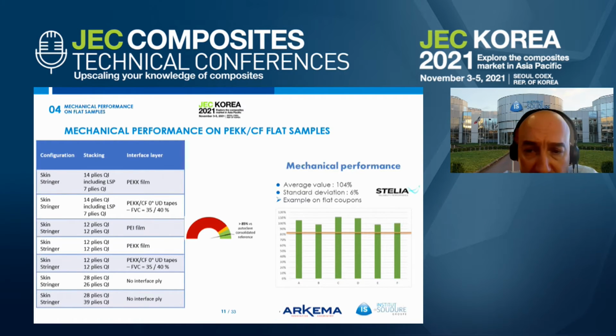If we have a look first on the right side of the slide, this is an example of mechanical performance that we can get on a study that we are running right now with Stelia, but this is illustrating what we get usually. So if we compare the mechanical performance of the welding joint with the reference, in this case, we are about 100%. So meaning that we are on target. We have the same performance between, I would say, the raw material that is consolidated in the autoclave and the performance of the welding line. So we have quite a good status right now. And this is what we are targeting for the next.